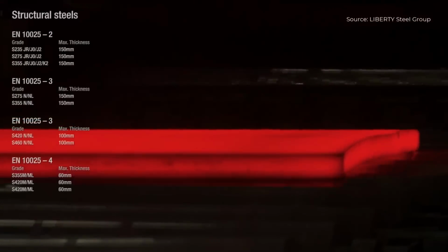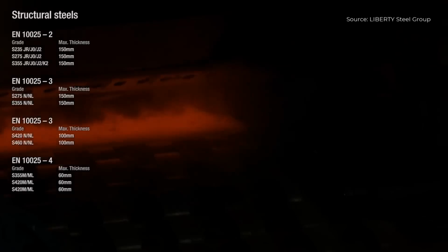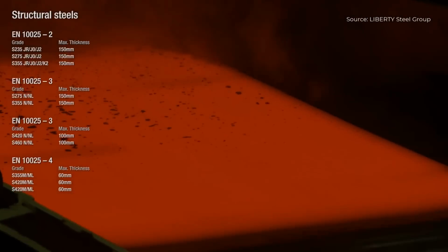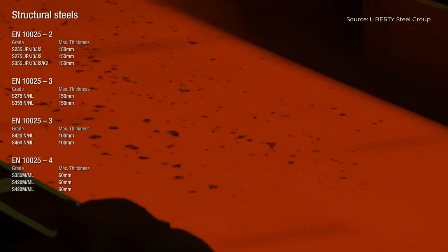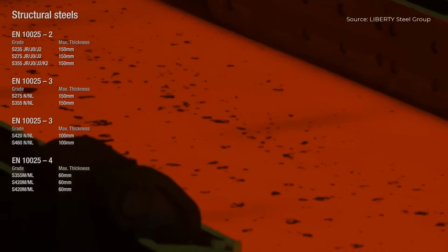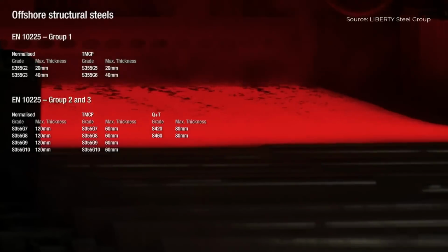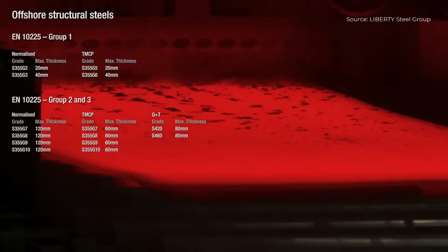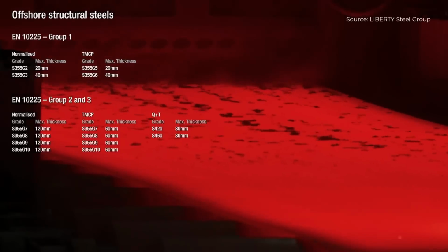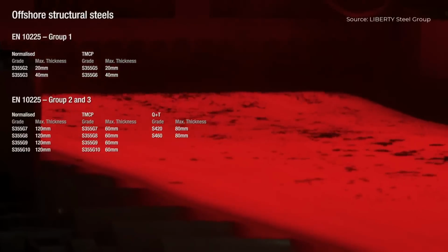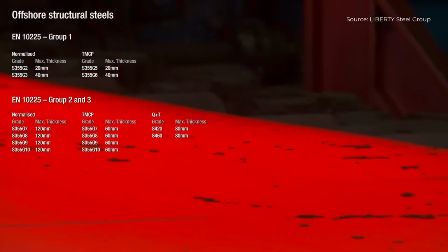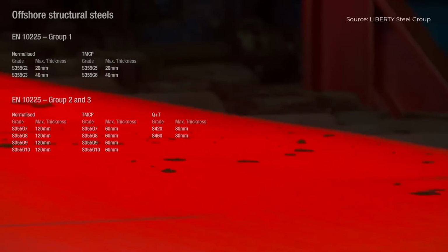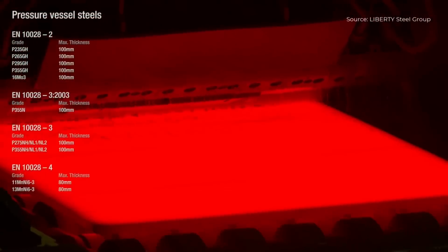At Liberty Steel Dalzell, steel plate production begins with heating steel slabs to approximately 985 degrees Celsius. These slabs are then rolled using a reversing plate mill, reducing thickness from about 290 millimeters to as thin as 15 millimeters. This rolling process refines the grain structure, eliminates internal porosity, and enhances mechanical properties. Depending on customer requirements, the plates may undergo further treatments such as normalizing, tempering, or thermomechanical controlled processing.